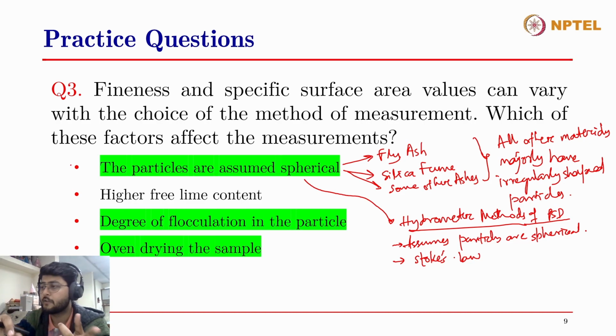This will also affect the results of fineness and specific surface area, because in most cases of cementitious materials, let's say clinker, limestone, slag or gypsum, cement, or metakaolin as well, they have irregularly shaped particles. So assuming them as spherical would only be an approximation and would not give us accurate results. The second is degree of flocculation in the particles.